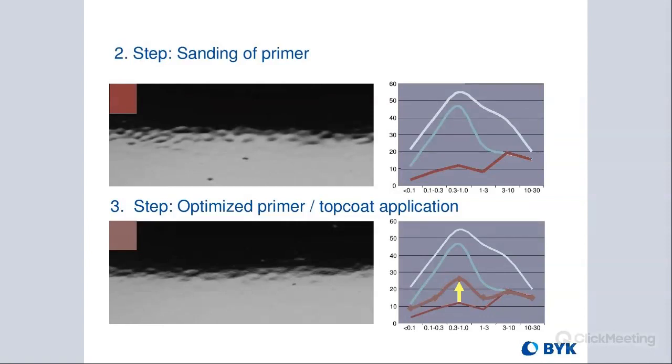There are a lot of different scales that are calculated in the Wavescan. Most of them are just various combinations of the dullness, long wave, short wave, and the various W values. And because they balance each other in various ways, it is important to take multiple values into account. And in general, when we're looking at the structure spectrum, we do want the short wave to be somewhat higher than the long wave.